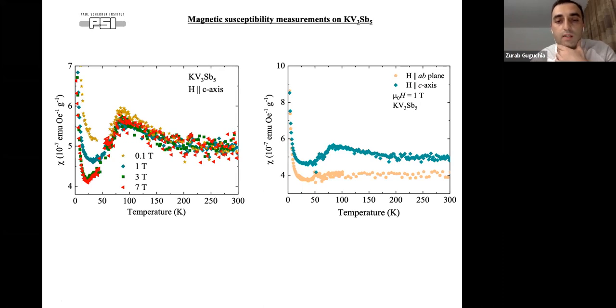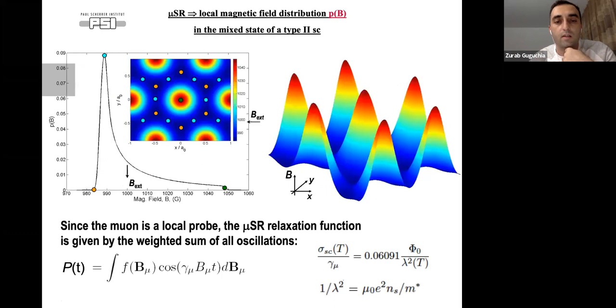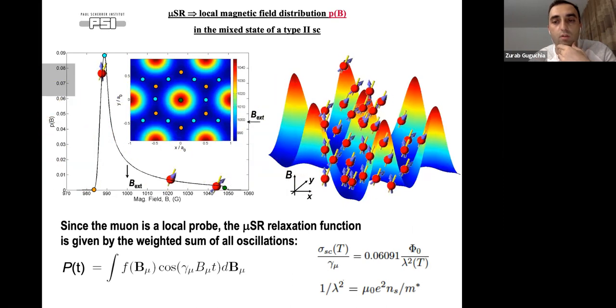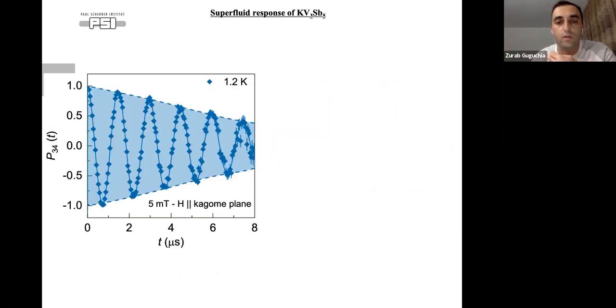So for the last 2 or 3 slides, I want to show you, since we think that the charge density wave is somehow unconventional, and there are some orbital currents involved in its formation, it's interesting to probe the superfluid density and the symmetry of the superconducting gap. So this we also do with muons, because we can shoot a lot of muons into the vortex state, and then we can probe the field distribution in the vortex state, and from this we can extract the magnetic penetration depth and measure it as a function of temperature, which is then sensitive to the topology of the superconducting gap.